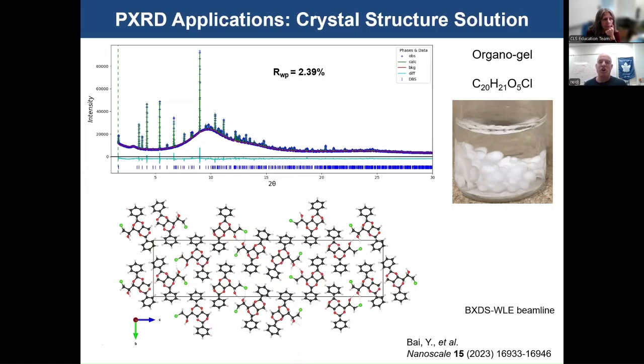It has a very long, skinny unit cell, which is illustrated by the black rectangle in the crystal structure here. And analyzing this data was very tricky. I would hesitate to say that you couldn't solve this structure with laboratory powder data, but it was hard enough using the synchrotron data that I don't think I would want to try it with lab data. It was that difficult.